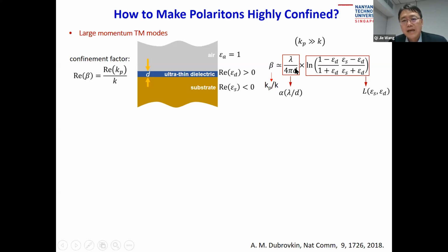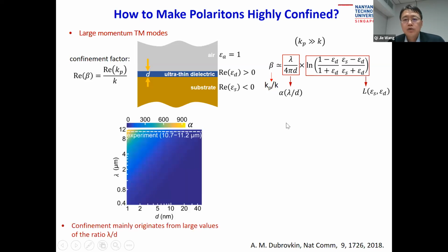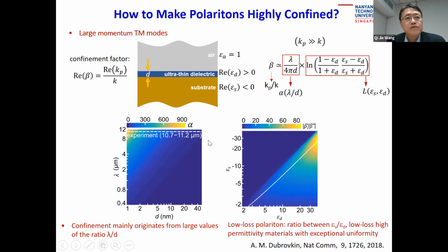The first term relates to lambda over d, where d is the thickness of this dielectric layer. And the second term is related to the logarithmic function of the dielectric function of that dielectric thin layer and also the substrate. So the key factor that determines the confinement factor is the first term, lambda over d. In a way, it shows that the thinner the dielectric layer, the higher the confinement you can achieve. And here shows the simulation result: lambda over d as a function of d, where lambda is the operating wavelength of the light, and this is the confinement factor. So you can achieve 1,000 times or even more. We also calculate the loss factor in such a system, which is determined by beta prime over beta double prime, as a function of the permittivity of the substrate and the permittivity of the dielectric layer.